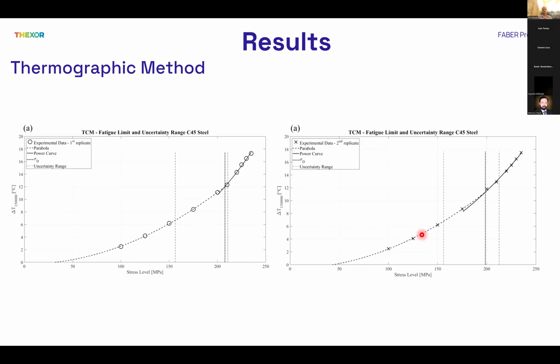If I focus a little more on this slide, you can see this range is the range of uncertainty, as written here. So the TCM method is fast, but in terms of reliability, due to the high range of uncertainty, it could not be considered the most reliable technique compared with the staircase methodology. You see that from upper 150 to a little above 200 is the uncertainty range, compared with the staircase method, where the exact number is 211 megapascal with a standard deviation of 5 megapascal.